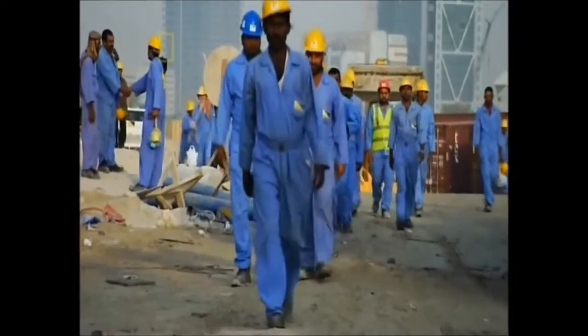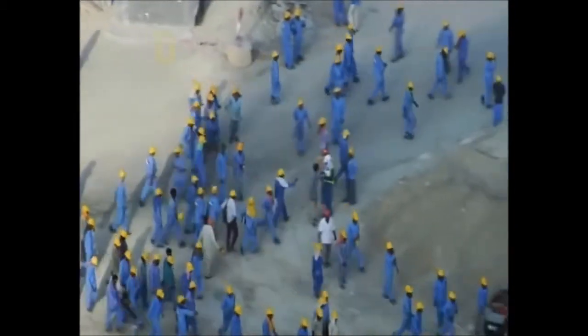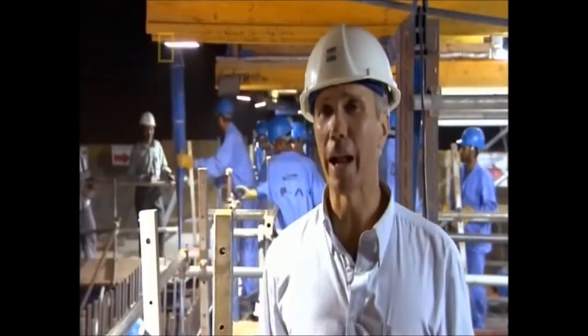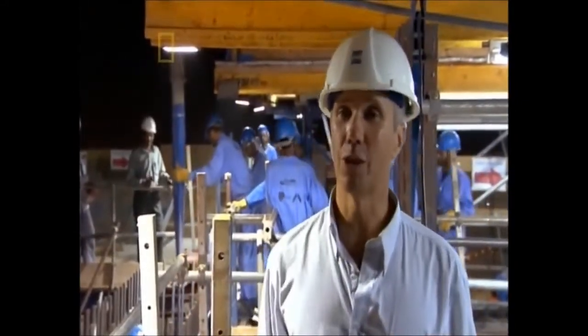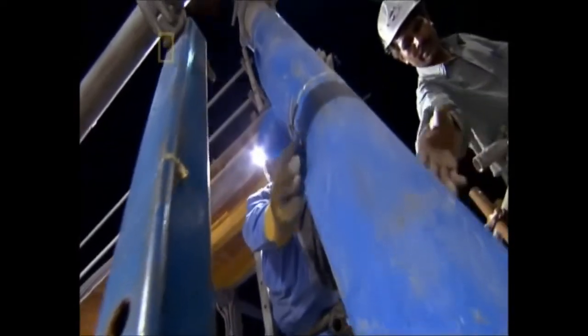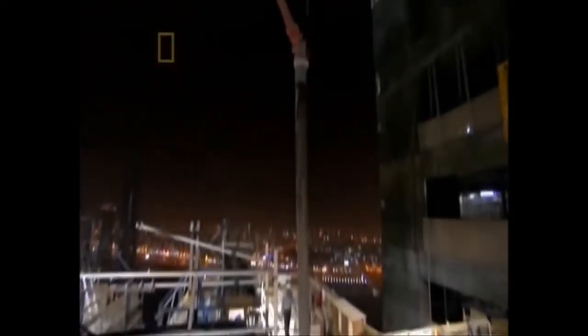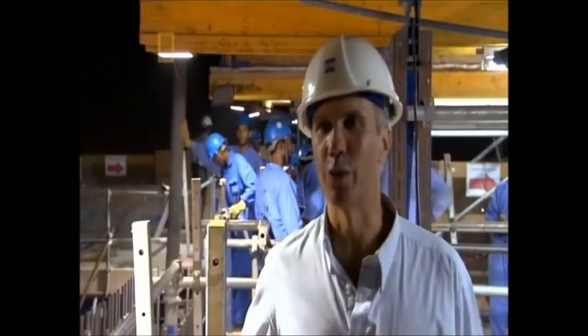As the sun sets, the second shift workers return to feed this growing skyscraper. The concrete pour takes place at night so that the concrete can harden evenly. At the moment, even though it's 10 o'clock at night, it's about 100 degrees Fahrenheit, and the humidity is about 90%. The advantage of pouring concrete in these conditions, because the humidity is so high, is we don't have a problem with it drying out the top surface of the concrete, but we've got effectively another roughly 130 stories to go.